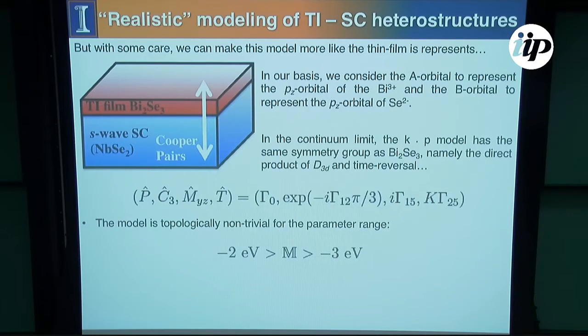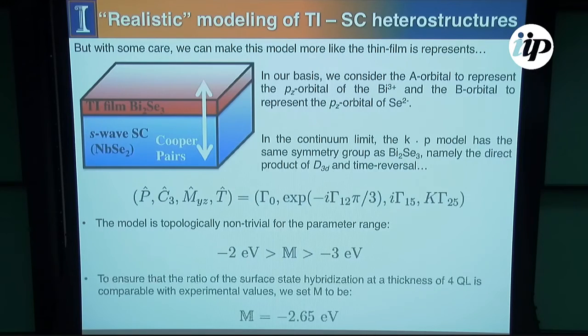so fine, it's time to choose a mass. And so it's topologically non-trivial for this parameter range. And for our particular system, we had a lot of access to exactly how large the gap was from ARPES data. So we were able to play around with the mass term until we got a hybridization gap exactly the same as the hybridization gap found in the experiments.